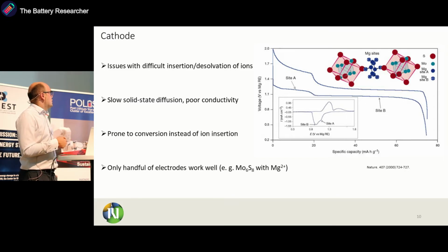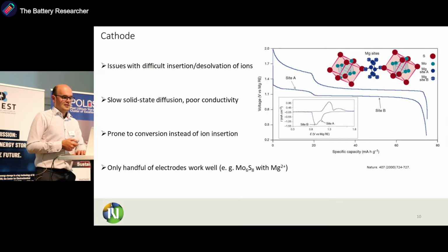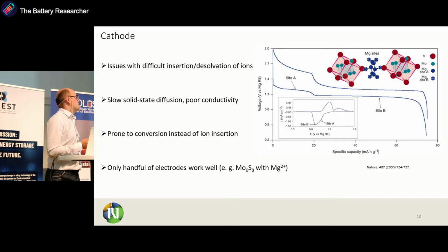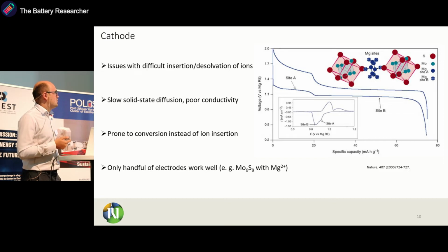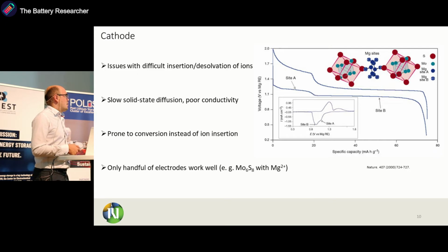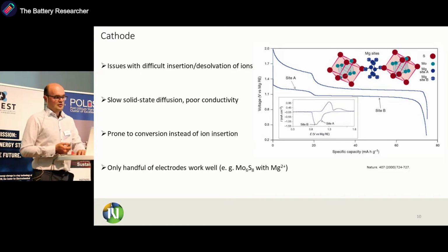We have issues with solid-state diffusion and poor conductivity, and also materials are quite often prone to conversion instead of ion insertion reactions. This leads us to the fact that basically the standard magnesium cathode material is still two decades old, the Chevrel phase, which was demonstrated by Aurbach in 2000. And unfortunately, we still don't have enough cathodes that would work really well. And this one, while it's well reversible, has relatively limited capacity and also only moderate voltage. So what can we do?